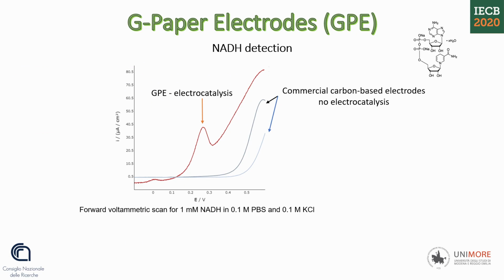Graphene paper electrodes were then tested for an application, the detection of NADH, which is a cofactor of several enzymatic reactions. A comparison with other carbon-based electrodes shows that the latter do not have electrocatalysis towards NADH oxidation, while G-paper electrodes can oxidize NADH at a much lower potential.